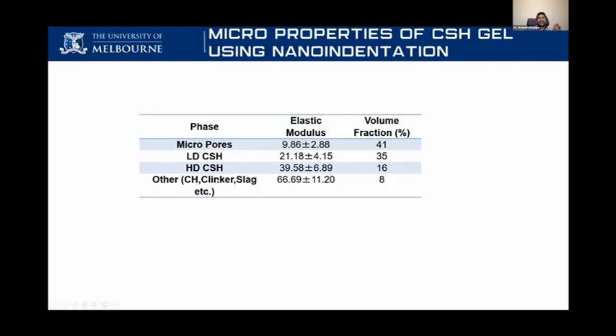But the clinker, this is an average value actually, but the clinker and slag have a higher elastic modulus and they are really contributing to the elastic modulus of the concrete as well as the strength of the concrete, because the clinker is really strong. It has a specific gravity of 3.1, compared with sand, for example, at 2.6, and concrete somewhere around 2.4, 2.5. But the slag has a specific gravity somewhere around 3. So they are very strong and they have a higher elastic modulus.